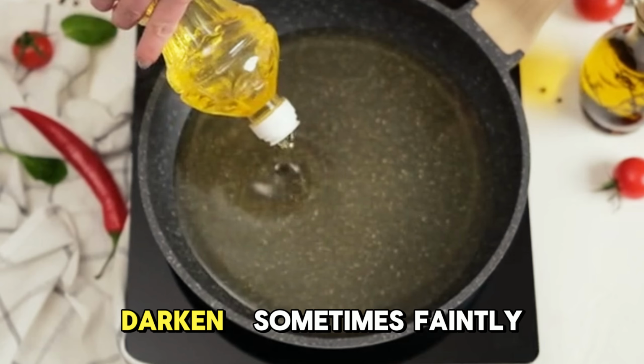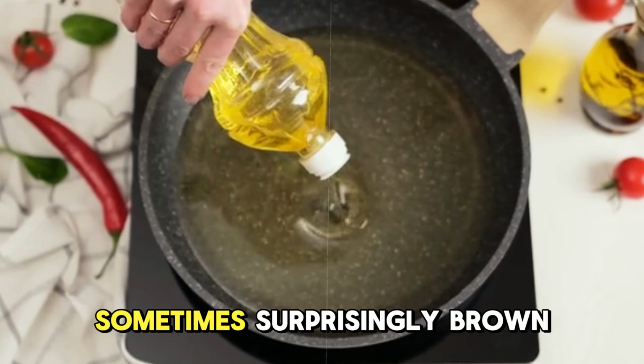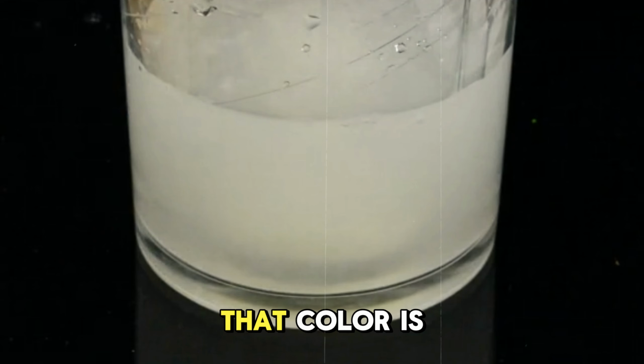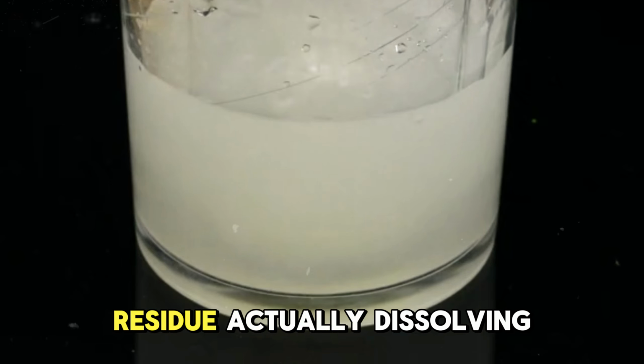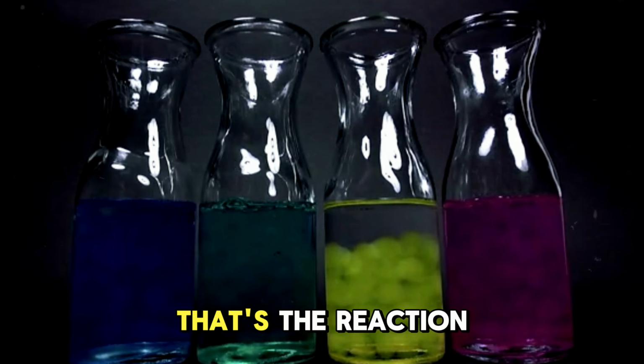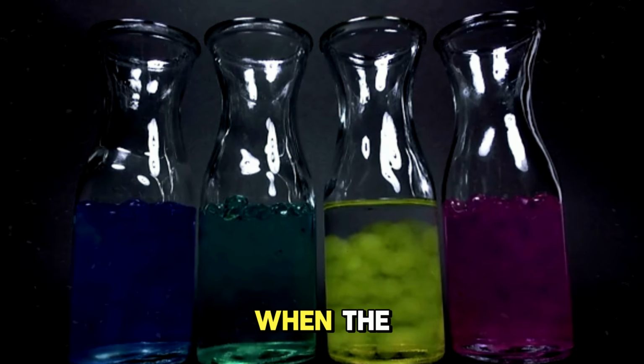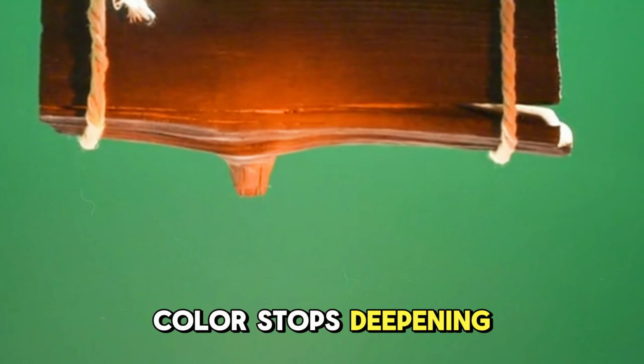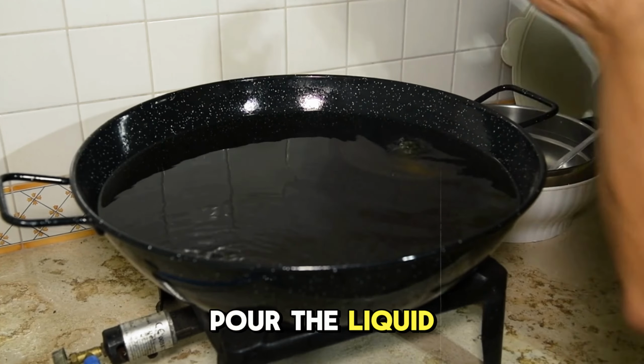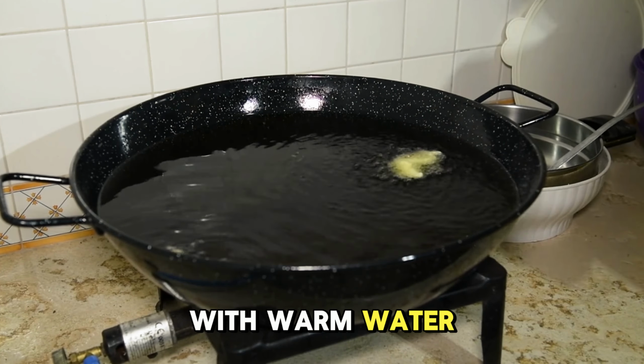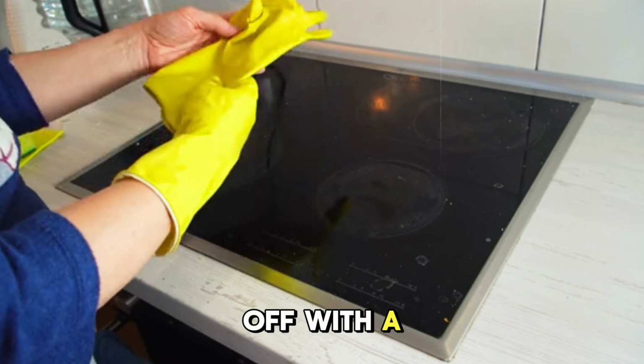You'll see the water darken, sometimes faintly yellow, sometimes surprisingly brown, and that color is the oxide layer and carbonized residue actually dissolving into the liquid. That's the reaction happening in real time. When the color stops deepening, the reaction has run its course. Pour the liquid out, rinse the pan with warm water. What's left on the surface, wipe off with a soft cloth.